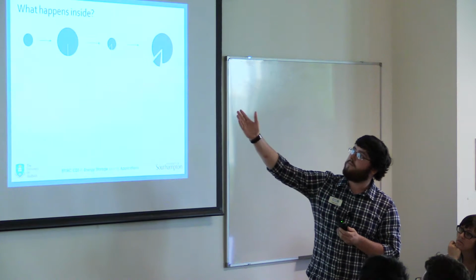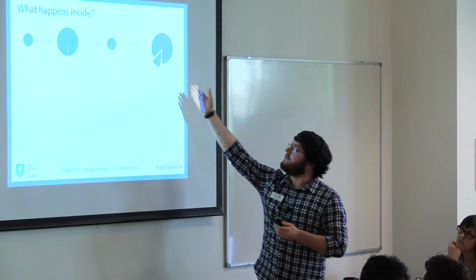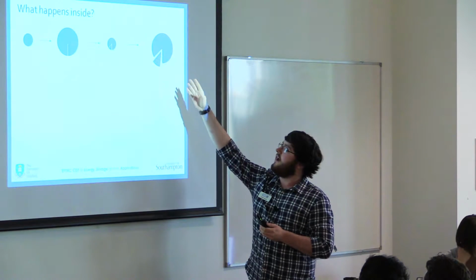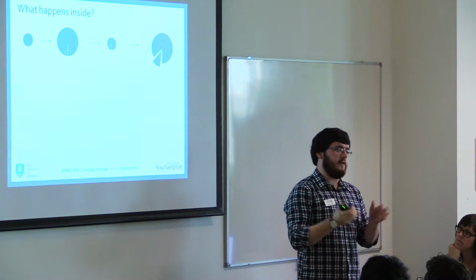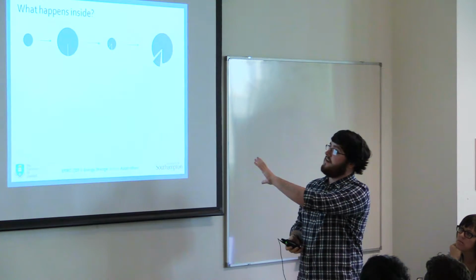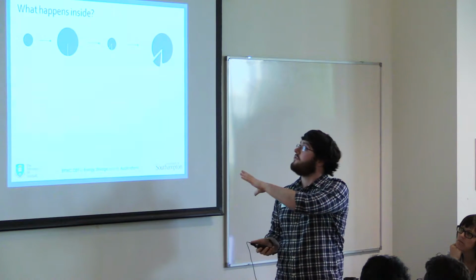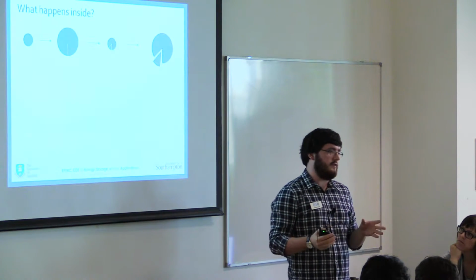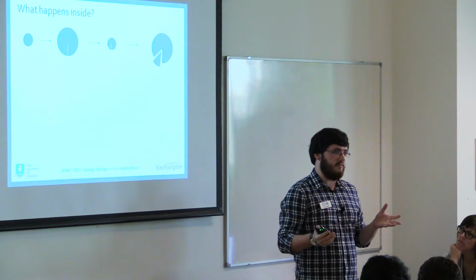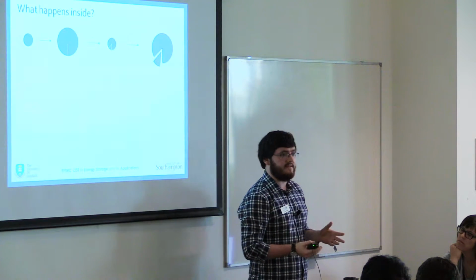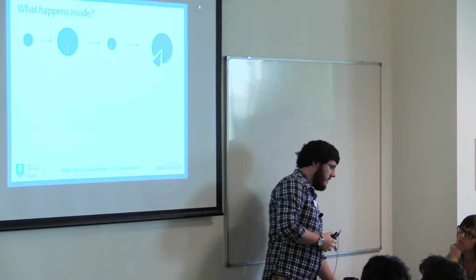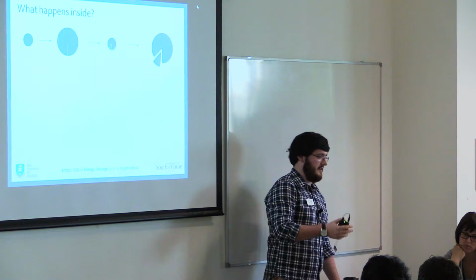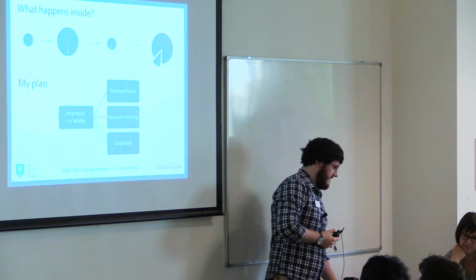You get cracks appearing in your electrode, and eventually you get severe cracks and parts of your electrode completely separate from the bulk, and that active material is lost. So the interconnectivity within the cell is broken down. You can no longer use that material to contribute towards the capacity of your cell. Obviously, there are other mechanisms in place, but I'll just pick the most simplistic for now.